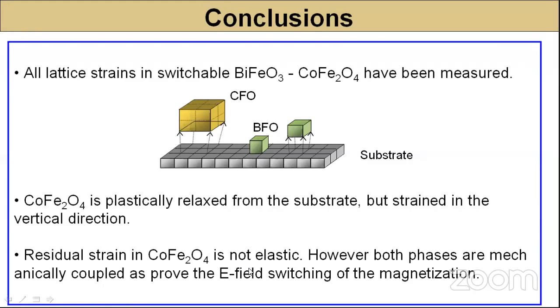Coming to the interface engineering part, I will quickly finish this. Strontium titanate is a band insulator. Both strontium titanate and lanthanum aluminate are band insulators. With strontium titanate, the band gap is around 3.2 eV, and for lanthanum aluminate it is around 5.6 eV. But if you put this lanthanum aluminate on a strontium titanate substrate and grow it epitaxially,